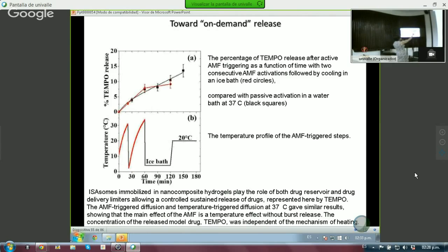Then what we could measure is the percentage of tempo release. In figure A, we have two results. One is the percentage of tempo released, and the second one, in black, is a blind test where we had a passive activation in a water bath. The water bath is maintained at 37 degrees centigrade, which is a little bit higher than the last temperature. And what you can see here is that there is really no difference within the experimental error bars between the two results.